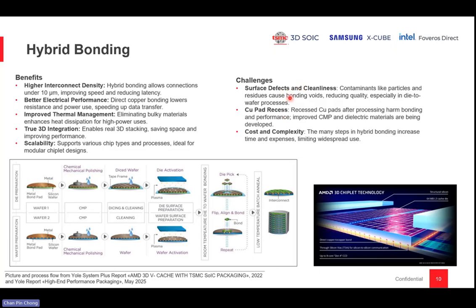All right. Some of the challenges, like I mentioned earlier, surface defects and cleanliness is important. So here you're interacting between two copper surfaces, copper to copper. Surface defects have to be absolutely clean. All right. Contaminants such as particles and residuals cause bonding voids, reducing quality, especially in the die to wafer process. And then, of course, the copper pad recess, where you recess the copper pads after processing, which hurts bonding and performance. Improved CMP and dielectrics are also being developed. And of course, you can see this flow here. The cost and complexity of this flow, with clean steps, activation steps, CMP steps, and quite a lot more steps added besides the traditional flip chip or TCB bonding, adds costs and complexities to